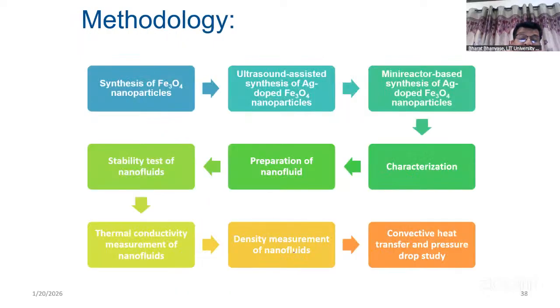So what is the methodology we used? That is synthesis of Fe3O4 nanoparticle. Fe3O4 nanoparticle synthesis can be carried out using FeCl2, FeCl3 addition, and then ammonium hydroxide can be added in that, which will lead to the formation of Fe3O4 nanoparticle.